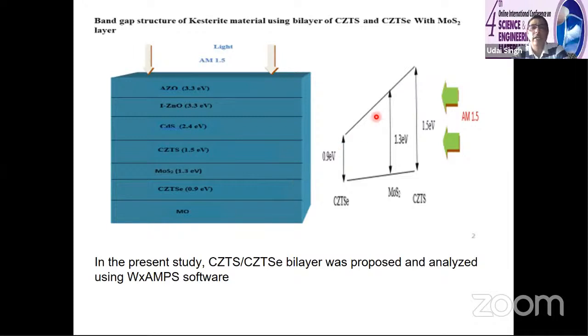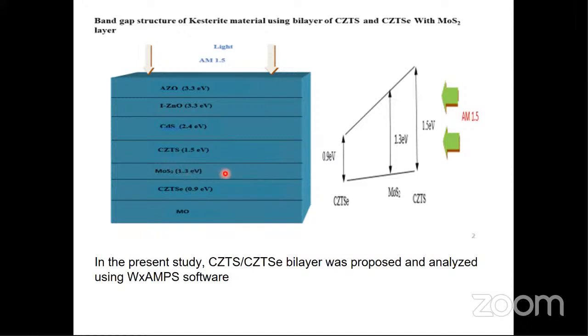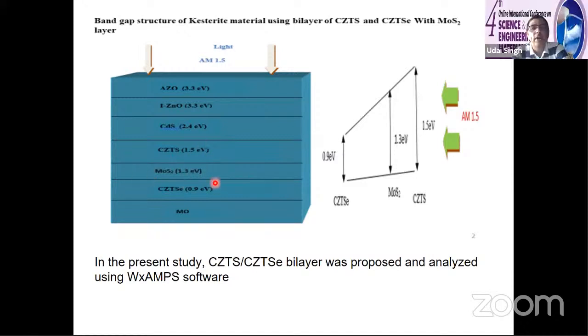It's a normal grading. So we have used CZTS as 1.5 electron volt and CZTSe here is 0.9 electron volt. And then we have introduced MoS2 just to avoid the interdiffusion so that the band gap should not change. So you have a grading of the band gap. Light is coming from this side, 1.5. You know, ZnO is around 3.3 electron volt, CdS 2.4. So most of the light will reach to this.